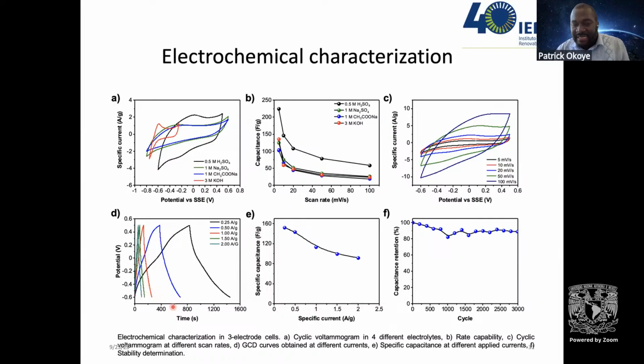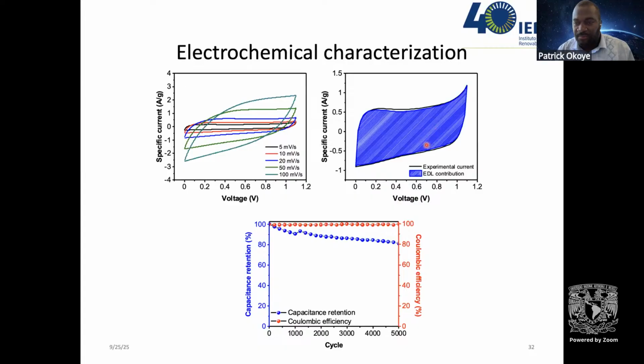One of the very fascinating things that we found in this study is that the DOE requires that the discharging time of that supercapacitor, or even hydrogen, will be in short minutes. So here we could achieve a very short time of discharge in this range, in seconds, for that matter. So the contribution of the electrical double layer we found from our study is quite huge compared to the Faradaic processes.